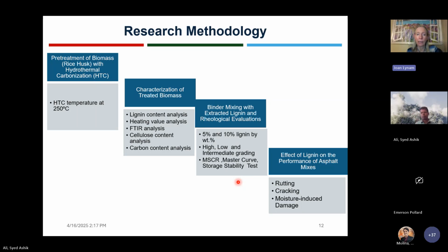And we did a lot of testing: high, low, and intermediate grading, MSCR, master curve, storage stability, and that sort of testing. And we did rutting, cracking, and moisture-induced damage testing. And this, Dr. Ali is going to talk more about. So we can go on.